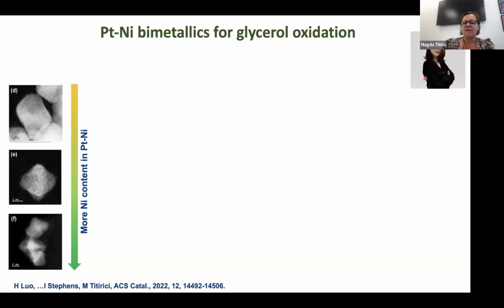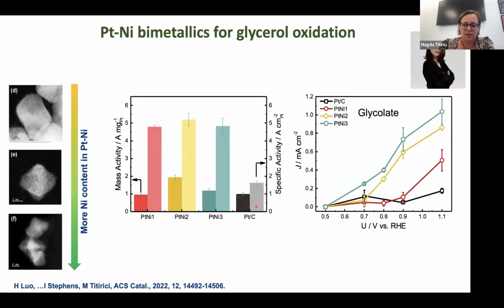This was done by a very talented postdoc that I have, Hui Luo, who's now a lecturer at the University of Surrey in the UK. And she thought, based on the literature, that platinum works the best for glycerol oxidation and does it at a very low potential, but it gets easily poisoned by the CO that you would generate during the oxidation of this. So she thought that we could modulate both the selectivity and increase the resistance to poisoning of the platinum catalyst by adding some nickel into it. And I don't have time to go into detail, but in particular, what Hui made was a pure platinum catalyst.